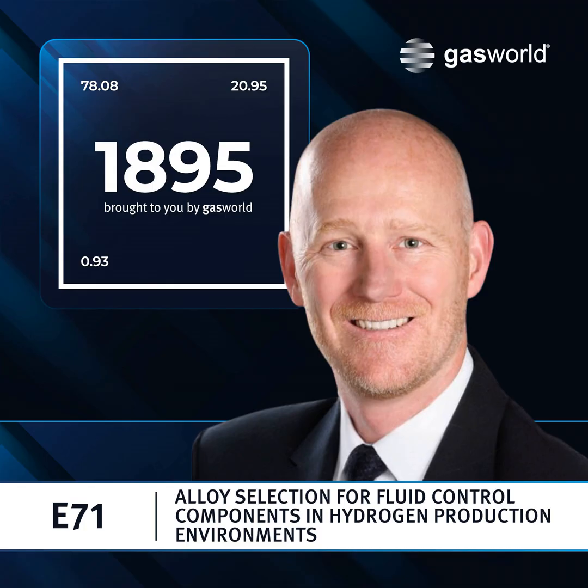So the process, the actual SMR reaction, again, happens around 700 to 1,000 C. The pressures are modest, 3 to 25 bar or 45 to 360 PSI. And the actual reaction vessels are fairly large and contain radiant burner tubes made of nickel alloys. The output of it is something called syngas, which is about 50% hydrogen with carbon monoxide and carbon dioxide. And there may be traces of impurities like chlorine or carbon or sulfur.